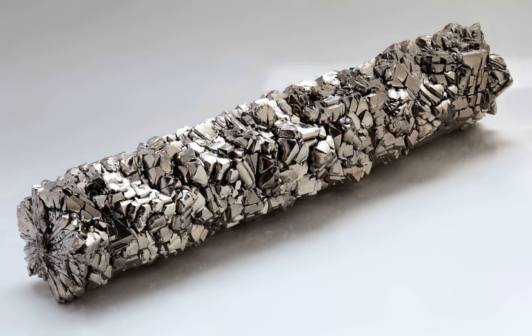When it first forms, this protective layer is only 1 to 2 nanometers thick but continues to grow slowly, reaching a thickness of 25 nanometers in 4 years. Atmospheric passivation gives titanium excellent resistance to corrosion, almost equivalent to platinum.